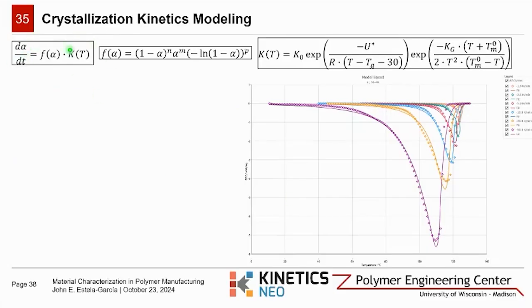Here we have our conversion model, where we have two equations on the right of it. We have the Sestak-Berggren equation and the Hoffman-Lauritzen equation. This model together expresses the crystallization rate as a product of these two functions, f of alpha, which depends on the degree of crystallization, and k of T, which is describing the kinetic dependence on temperature.